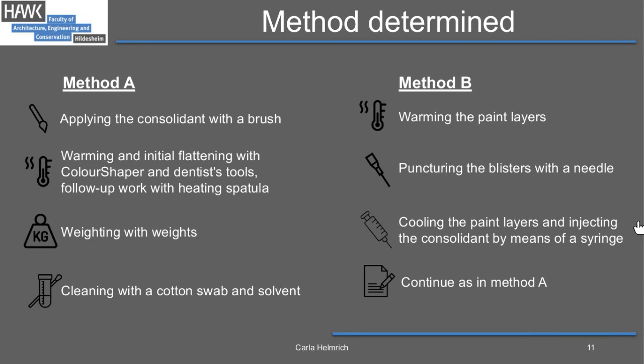In contrast, method B is for blistered areas that are particularly large and have an intact surface. They must be treated separately. These areas are first heated by the infrared lamp. A small needle is then used to puncture the softened blisters. After the paint layers have cooled down, a small needle and syringe are used to inject the consolidation agent into the blister. So these two steps are pretty time consuming. The surface is then evenly treated with the agent drop by drop. After another 12-hour evaporation period, the blisters can be flattened as described for method A.